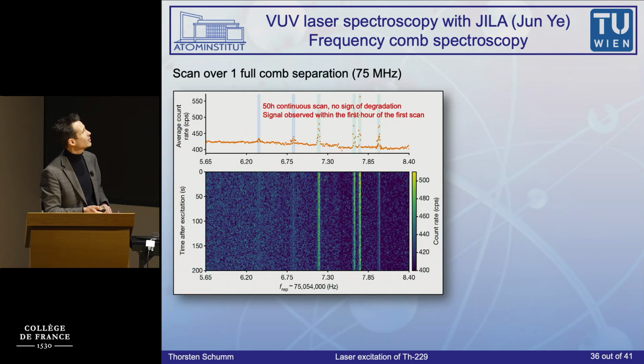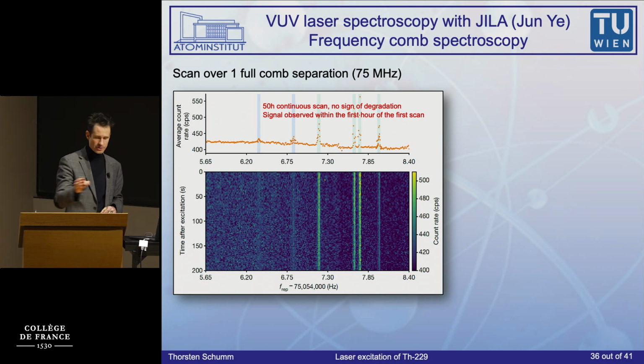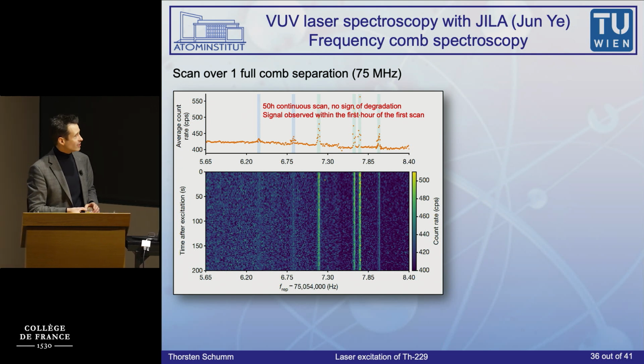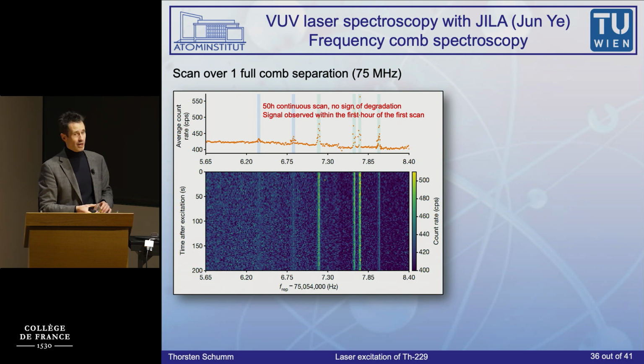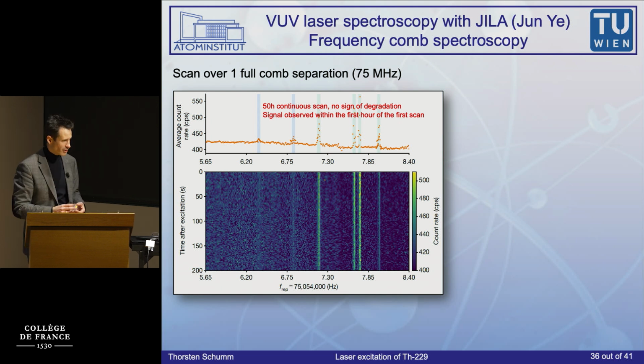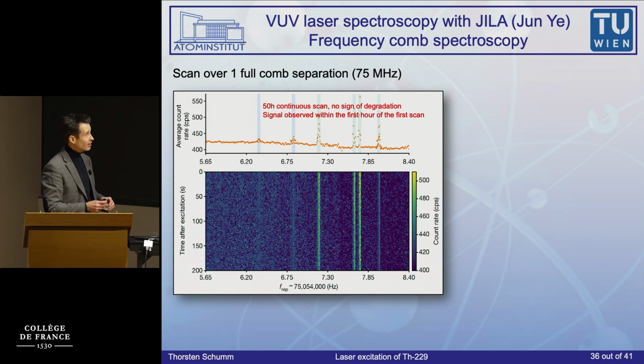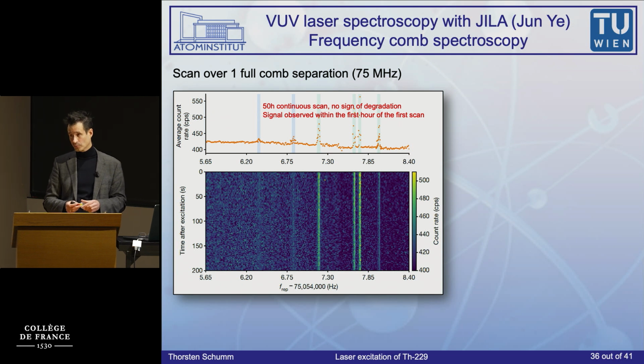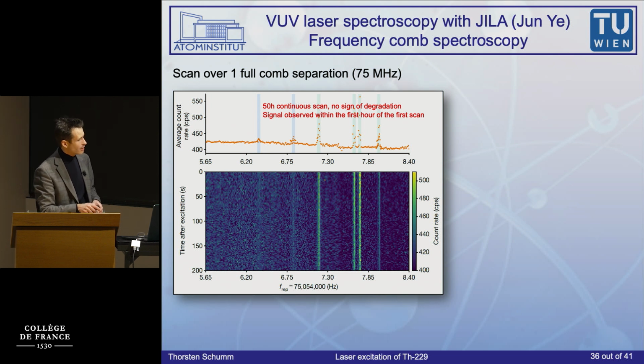That's a known technique. Okay, so we did scan again with this laser over the nuclear transition, and to our, well, I hope at least to your surprise, not to mine, because I hoped that would happen, we see more than one line. We don't see a two-level system. We see, well, you see there's absolutely 4, maybe there's 2 additional lines here.